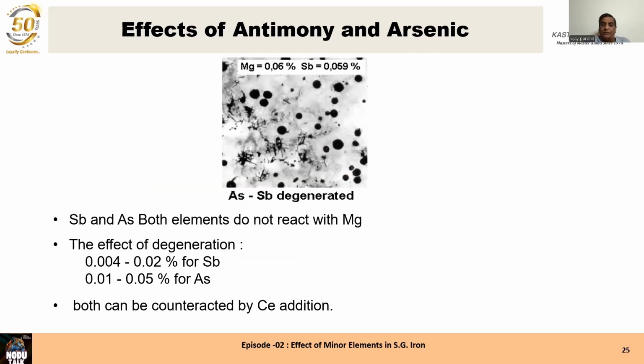You look in the microstructure with arsenic and antimony degenerated the graphite. The graphite particles are nodular in most cases, but in between the nodules, these are the cell boundaries. In between the nodules, you see the graphite has been generated and formed mesh graphite, spiky graphite, flake graphite, and this is what will cause deterioration of all the mechanical properties of SGI.